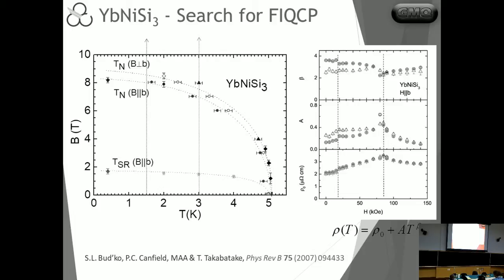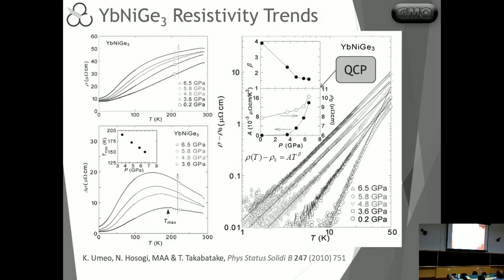And pressure doesn't help in this case because it's just going to make the sample go further away since it's already ordered. When we apply pressure on ytterbium, it just goes further away from the quantum critical point. So what we did then in this case was turn our attention to the germanide, which we expect to have a larger lattice parameter, which would then represent negative pressure. And indeed, when we look at the germanide one, it is a strongly mixed valence system that does not order. So this one would be appropriate to look at the pressure-induced quantum criticality.